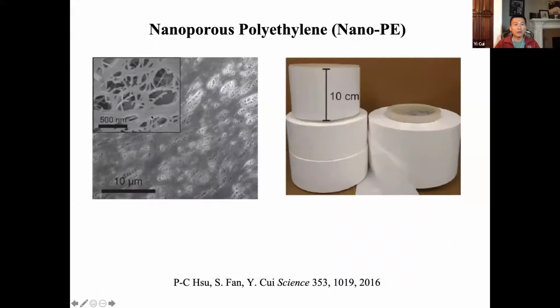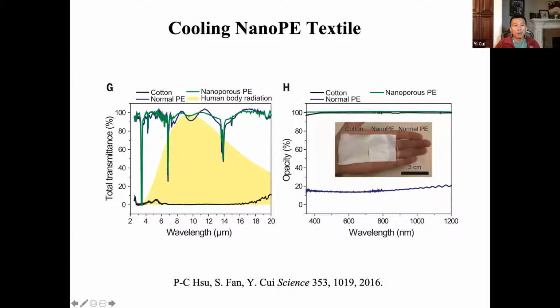So we started to engineer nanopores in there, right? At a few hundred nanometer scale, they scatter visible wavelength of light, 400 to 700 nanometer. Now you see this white colored polyethylene. This is, for convenience, a battery separator. My lab has been doing battery for 15 years. So the first time we measured this battery separator, we found out it's really, really cool. It allows the infrared transmittance, going out, right?